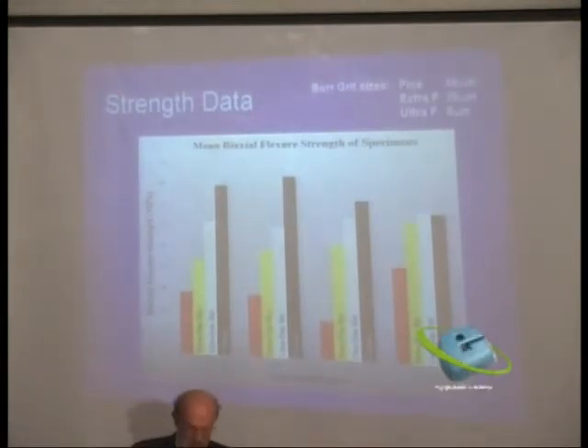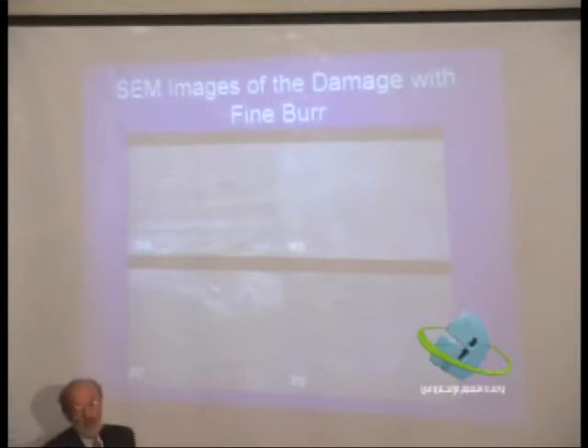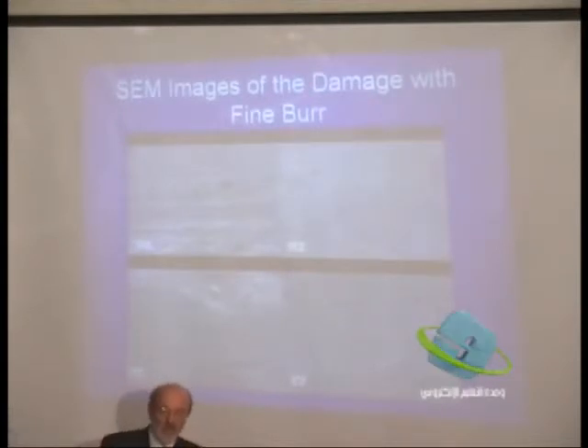But what caused the damage? When he went to the SEM and looked at these samples, here is the cut area across that surface, he saw these crack patterns. These crack patterns are thermal shock cracks. So what is happening? In the trace of dragging the burr across the surface, you get very high temperatures generated because of the cutting of the porcelain. But because the turbine is running at such high velocity, it doesn't enable the water to get underneath the turbine to cool underneath the cutting. As soon as the burr moves away from the area it's been cutting, the water can quickly quench that adjacent area, and that causes this cracking pattern that reduces the strength of that material.